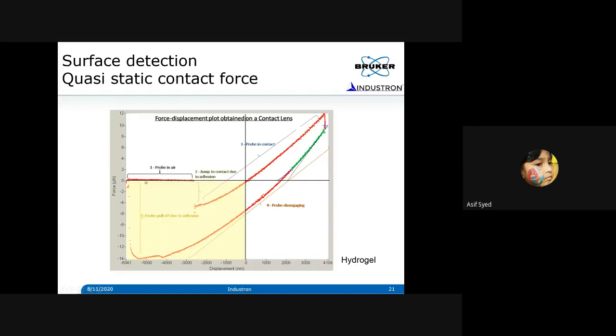So the probe is in contact. If you can follow my cursor, then jump to contact. These are all happening in the adhesive interaction regime. And then as you increase the force, it becomes negative to positive, zero, and then positive. The positive force regime is what we call repulsive interaction, right? So normally the repulsive interaction is what we measure as the load displacement response to measure the properties of the material. But on soft materials, you need to measure the whole thing, okay? That is the first mistake that people make.